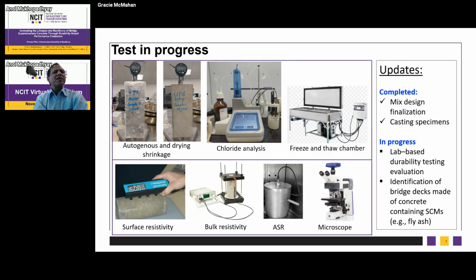Okay, so for the tests, our job is to reproduce the mix of the BEAST facilities at Rutgers. We reproduced the mix and did the sample casting. Several tests are underway, like the autogenous shrinkage test, chloride test, freeze thaw durability, bulk resistivity, surface resistivity, alkali silica reaction, and petrography. So mix design finalization and sample casting are done, and all the lab tests are in good progress. And of course, we are going to identify some bridge decks that contain SCM, like fly ash. Go to the next slide, please.